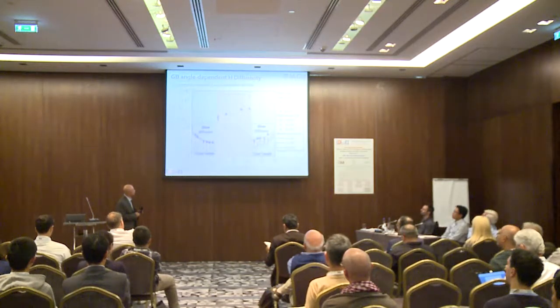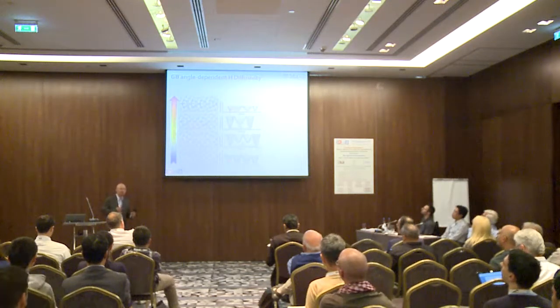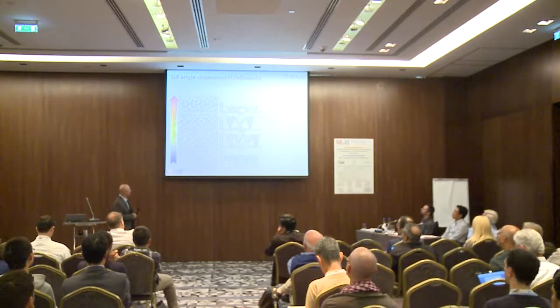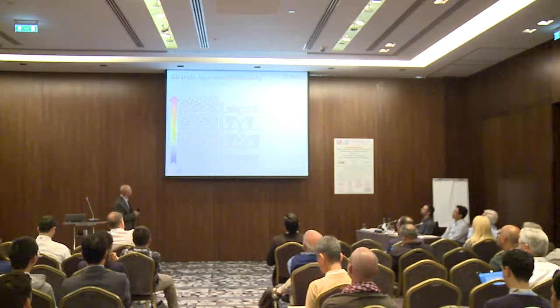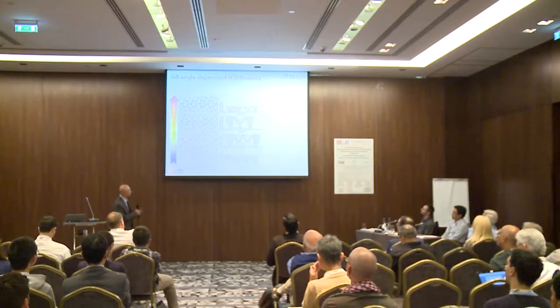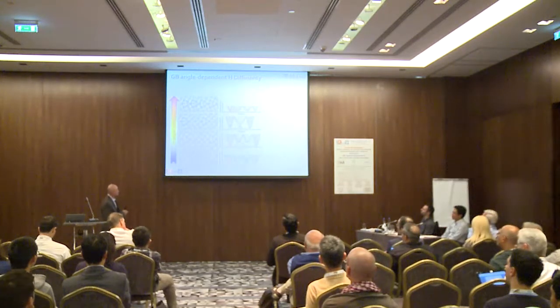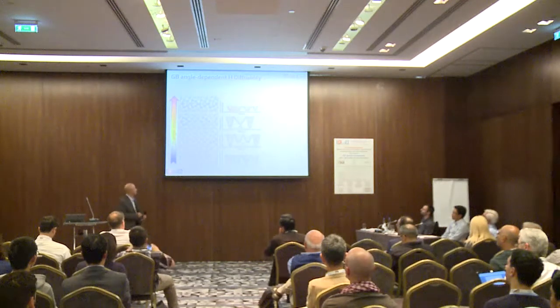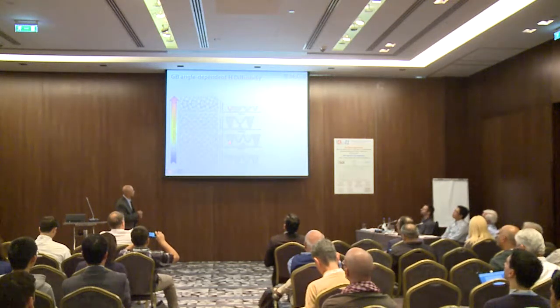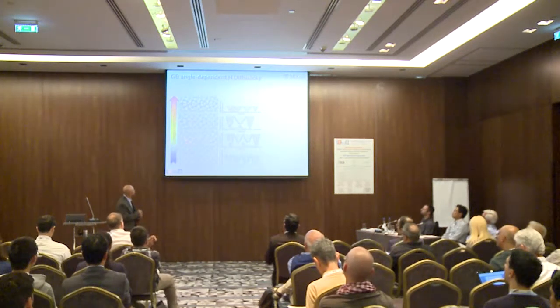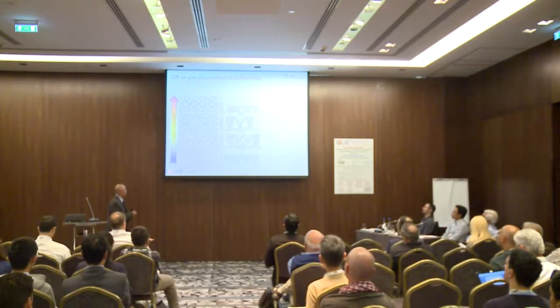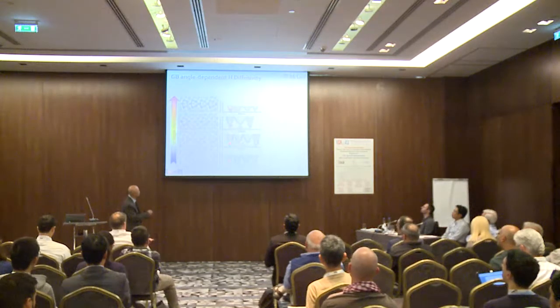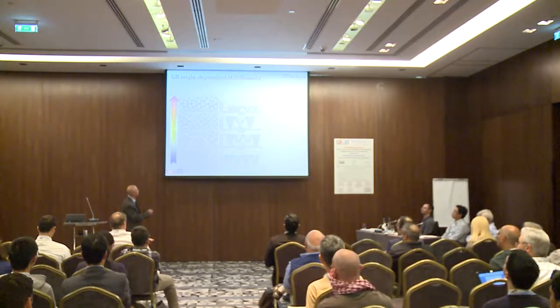For low angle, we know that we can nicely use a dislocation model to describe it. With the angle small, you can describe the grain boundary as a series of dislocations spaced along the grain boundary. And we know the dislocation serves as a trap site. So basically this would be the energetics, the picture you expect. And the trap site means that the energy state is lower, so it effectively traps hydrogen and gives an effective overall high barrier, although at the core region you can have a low barrier region. But basically this is what you expect. So this is an individual low barrier region, a high barrier region, and then followed by the bulk diffusion.